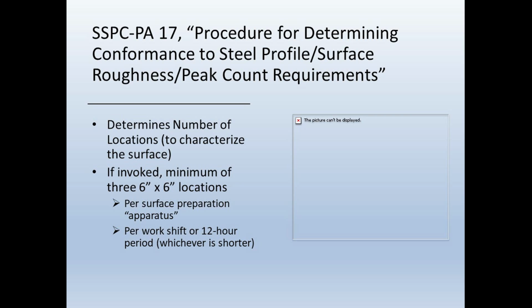Now, PA17 says, okay, you're going to use the replica tape, you're going to take 2 readings per area. You're going to use the depth micrometer, you're going to take 10 readings per area. Now, how many areas are you supposed to check? This is where PA17 kicks in. And it says for whatever was blast cleaned in a shift, in a work shift, you check a minimum of 3 6-inch by 6-inch locations.